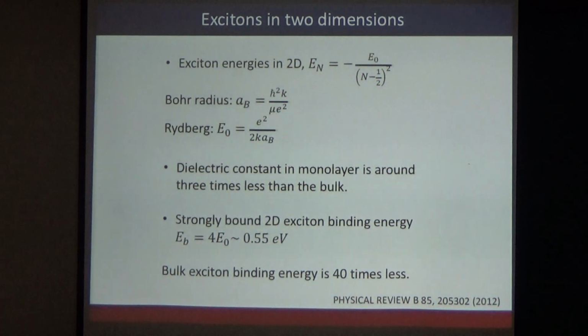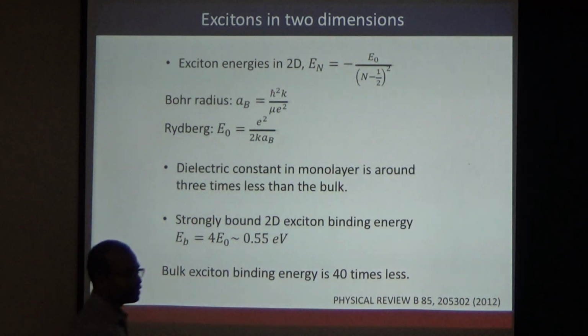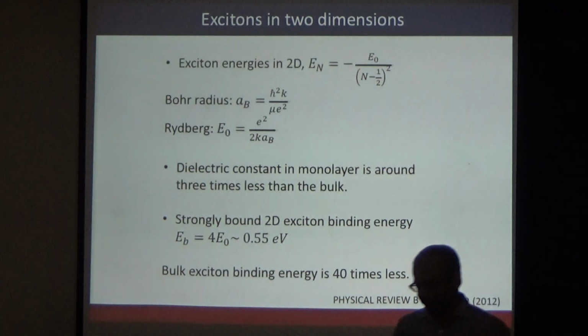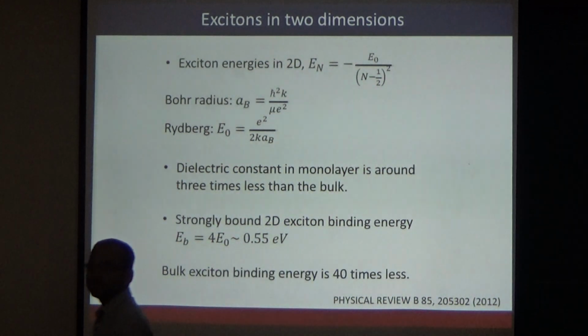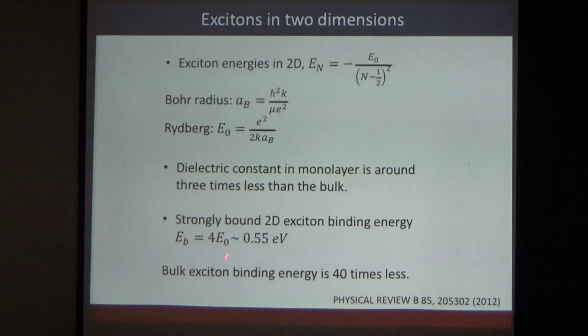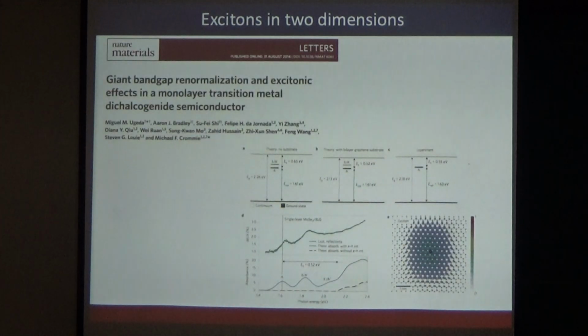As a result, you get a binding energy that is 4 times the Rydberg energy, and that will give you a binding energy which is experimentally verified, that is 0.55 electron volt, which is huge in the sense that you can even get a stable excitonic state even at room temperature, because room temperature is around 25 milli-electron volt, right? So you'll be able to see these excitons even at room temperature, very stable, right?